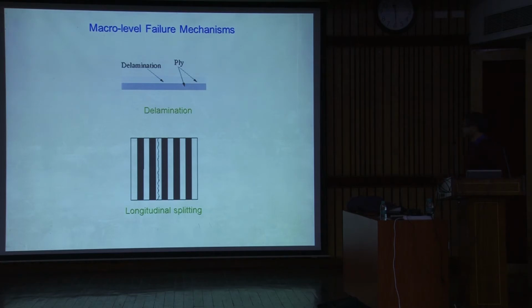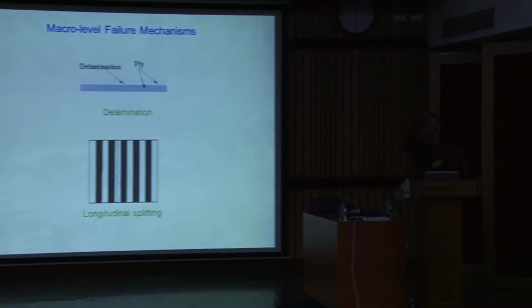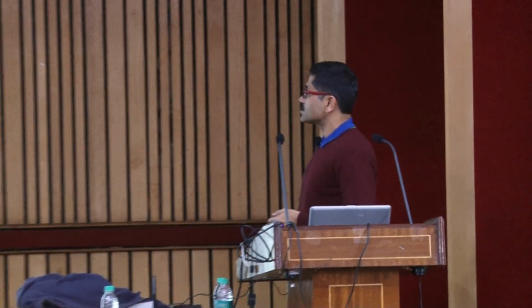And as I said in the previous slide, the ply can split along the fiber. So, the crack that has developed in the matrix material goes along the fiber length through the thickness of the ply and the entire ply is separated. So, this is called longitudinal splitting.